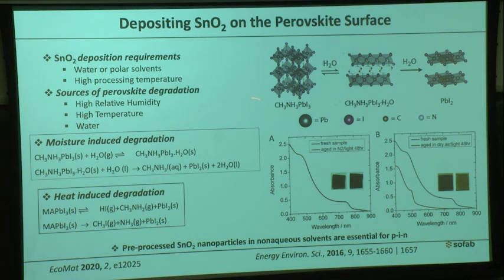When a perovskite comes in contact with water, it undergoes degradation. Another way we can deposit metal oxide directly on top of the perovskite is by depositing a precursor and heating to high temperature, but if we heat perovskite to high temperature, it also undergoes degradation. That's why to deposit tin oxide directly on top of the perovskite, we need pre-synthesized tin oxide in a perovskite-compatible solvent, which is a very challenging job.